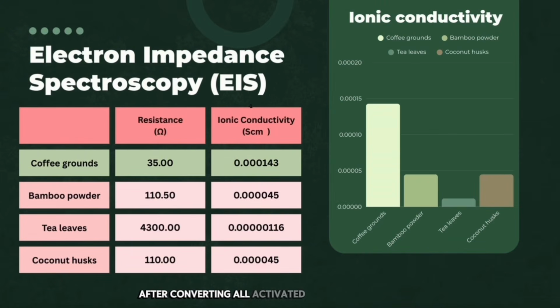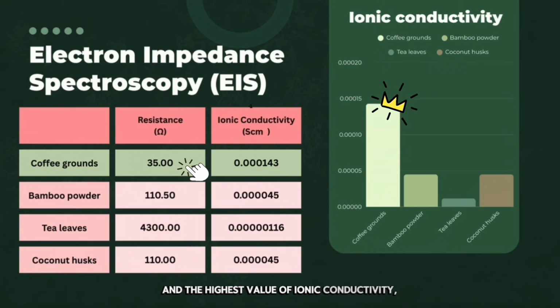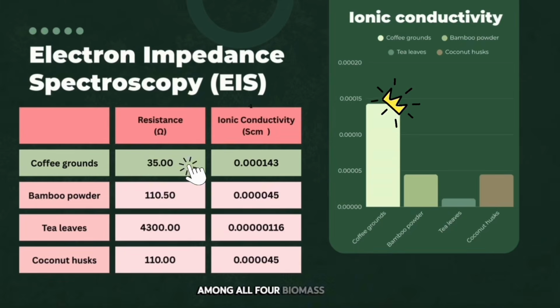After converting all activated carbons into anodes and testing them using electrochemical impedance spectroscopy, we found out that the activated carbon from coffee grounds has the lowest value of resistance and the highest value of ionic conductivity, making it the most promising material for anode for lithium-ion batteries among all 4 biomass wastes.